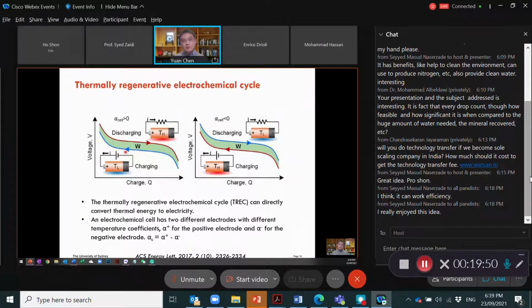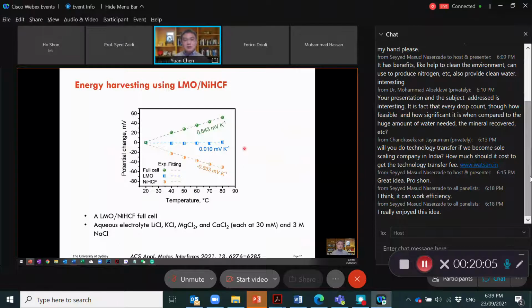On the opposite side, of course, if you have a negative thermal coefficient, then you do the discharging at the low temperature and the charging at the high temperature, and then they can also generate electricity. So then the question is, can we use the neutral pair, which is LMO and the nickel HCF, which people have been using for lithium extraction, to harvest energy, particularly in our aqueous electrolyte environment, which is similar to the brine or the salt water which people use as the liquid source to extract the lithium? So we did the test, and here you can see that.